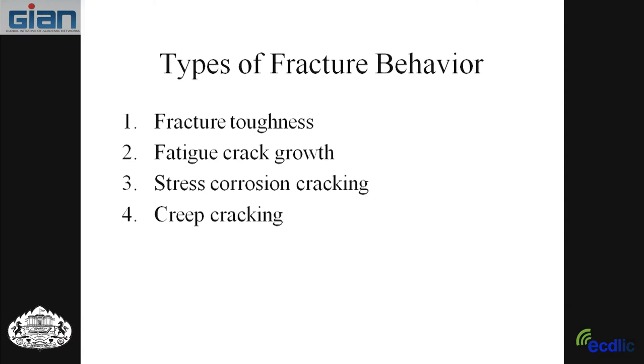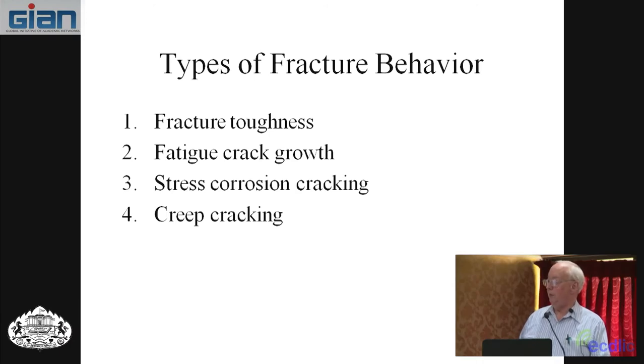The type of failures can talk about then fracture toughness, which is failure under a monotonically increasing load, failure due to fatigue, which is under cyclic load, failure due to stress corrosion cracking, which is the combination of a bad environment with stress and cracks, and then if you work on high temperatures, sometimes people worry about creep cracking.